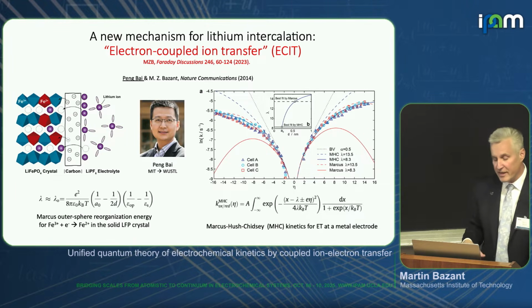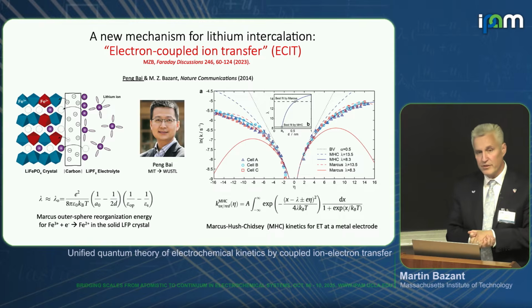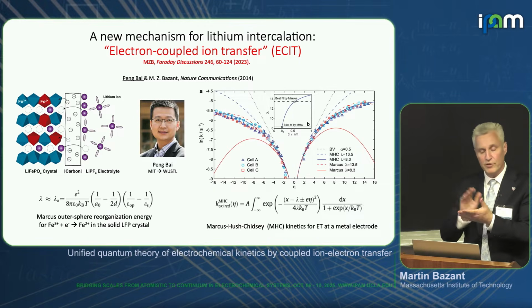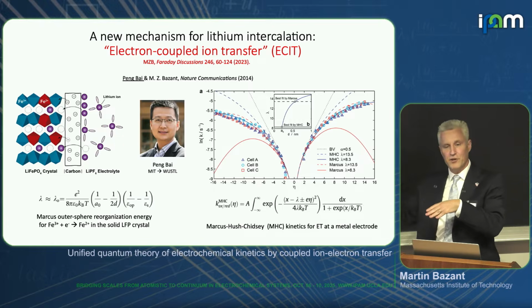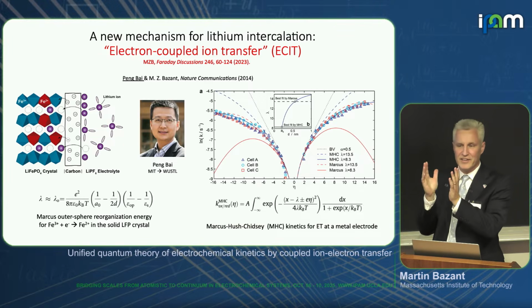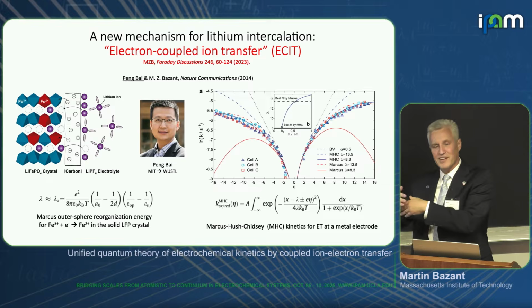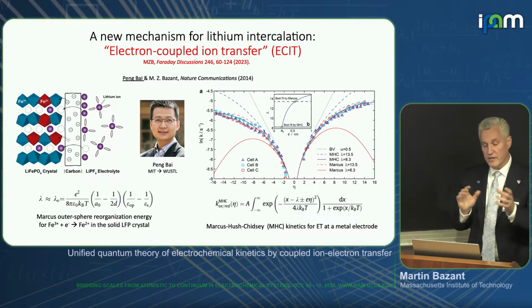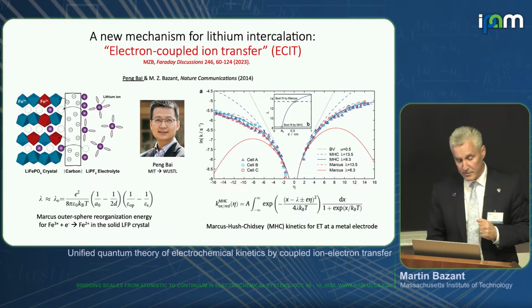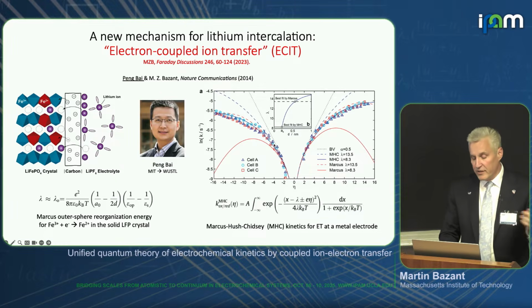And so we had to deal with that, but we devised an experimental method by taking small pulses of potential and seeing how the current rises and falls. We modeled the rising part of the current as nucleation and the falling part as reaction limited, and that way we measured and inferred reaction kinetics, assuming we were reaction limited in our experiments, and basically plotted here the log of the rate constant against the overpotential.